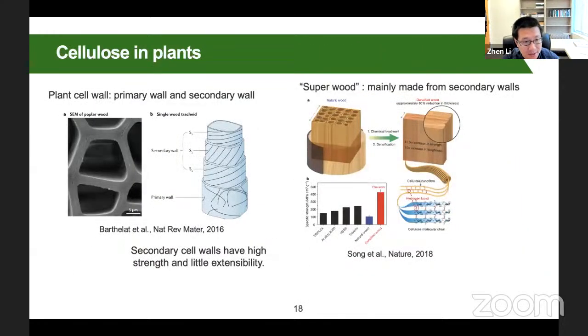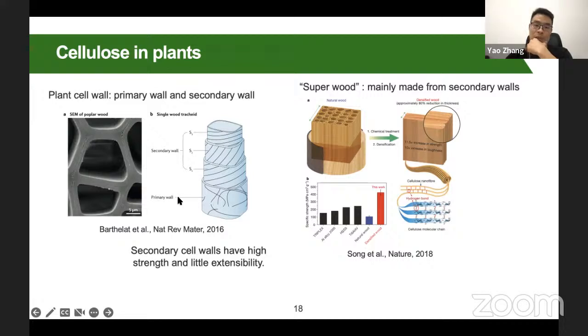So what's the main difference, using the same material, that gives plants significantly different strengths or mechanical responses? Yeah, it all depends on the composition and the structure of the primary cell wall and the secondary cell wall. First, the mass percentage of cellulose in these two cell walls is different. In the secondary cell wall, I think the dry mass is around 35 percent cellulose, but this is not the case for the primary cell wall. In the primary cell wall, the percentage of cellulose is much lower. And also for the primary cell wall, I think 80% is water. So you can consider the primary cell wall as a hydrogel. Actually, okay, it's a hydrogel.